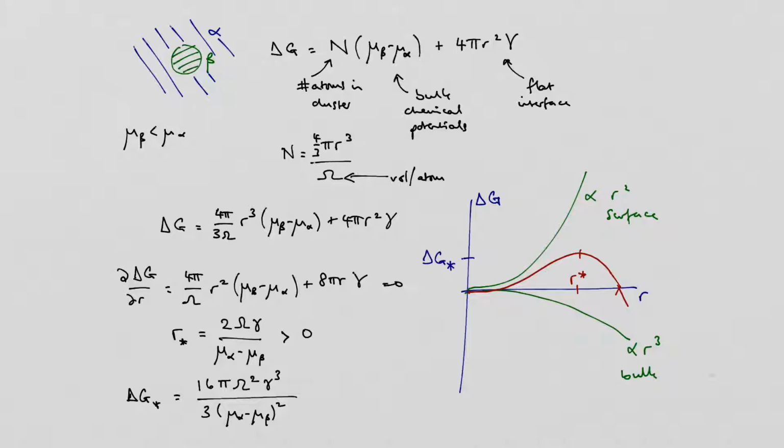Suppose there's a fluctuation that happens here, and it will tend to shrink back. If a fluctuation just manages to get over the barrier, then it will grow. The chances of it happening are very, very small, but you've got Avogadro's number of them around, so it will happen sometimes. And the ones that get over this will then spontaneously increase in size. They will then grow.